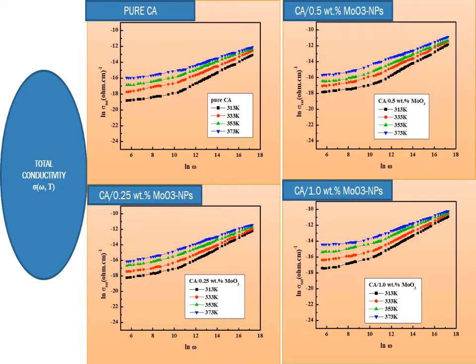Total conductivity is drawn as a function of frequency and temperature, and it was observed that at low frequency the total conductivity is nearly constant and then increases with increasing frequency. This behavior is like many solids and polymers, and we observe it in all our samples. The total conductivity also increases with increasing temperature. From the intercept of the total conductivity curve with the y-axis, we can calculate the DC conductivity, and then we subtract the DC conductivity from the total conductivity to get the AC conductivity.